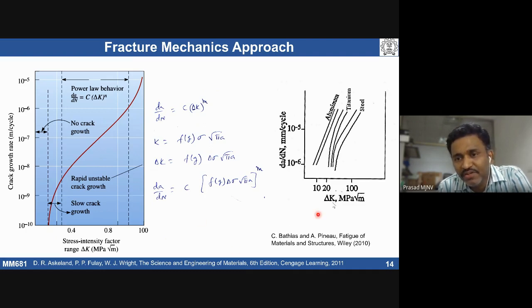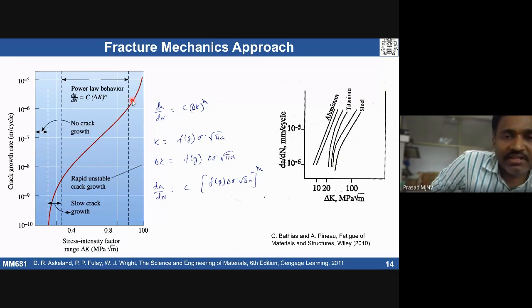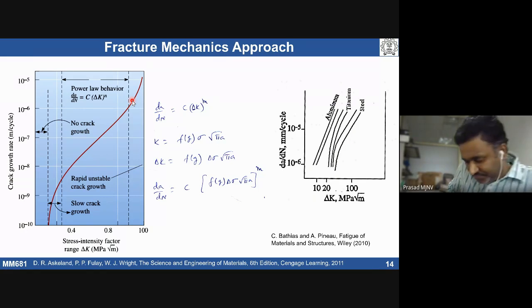So if I look at some standard materials, steel, titanium, aluminum, typically we'll get a curve like this. Depending on the strength of the material, we do see that the delta K is also going to change. For example, the threshold that you are seeing is going to be higher for steel as compared to titanium, as compared to aluminum. So this is how people establish this kind of curve for different materials in a lab scale. Then we can understand how this particular material is going to behave under cyclic loading conditions.